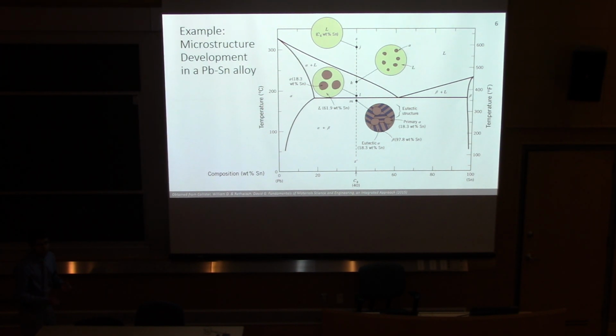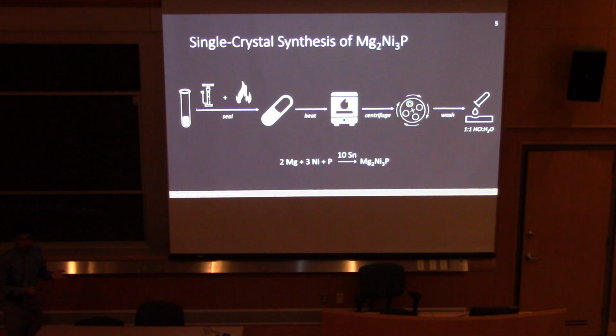So what we want to try and do is allow for our system to slowly cool from the liquid phase to the liquid and solid phase region to form crystals in a liquid matrix, after which we immediately take it out and get rid of any sort of liquid that's remaining. So with that in mind, we then go to the single crystal synthesis.